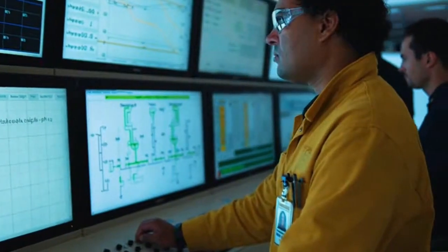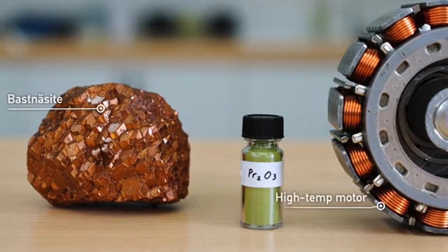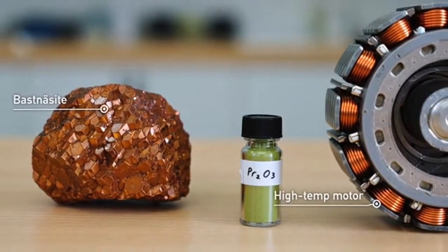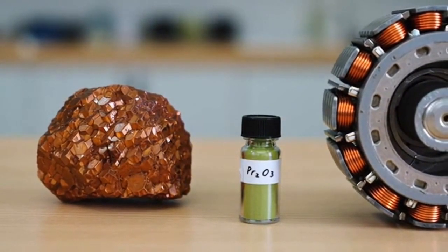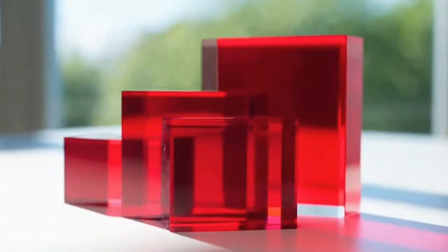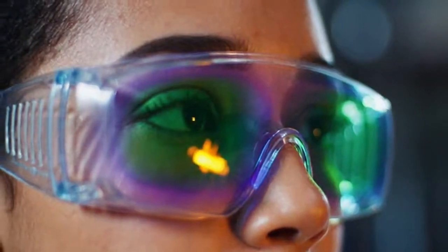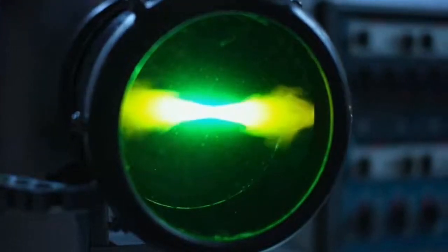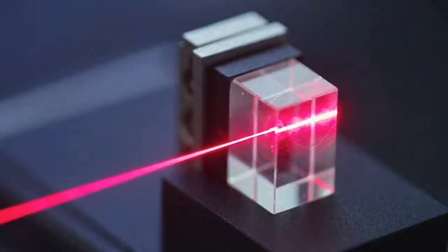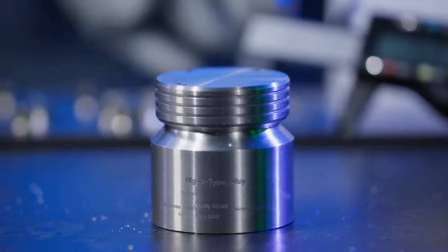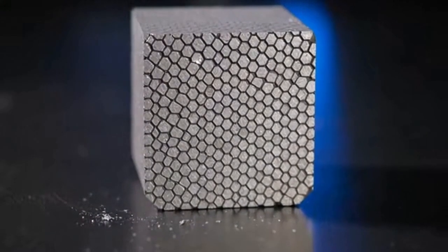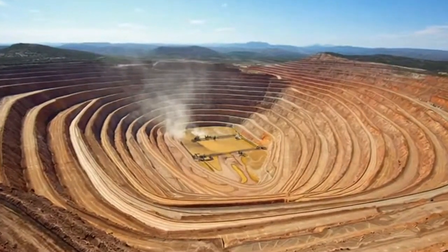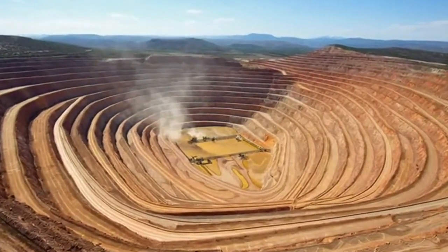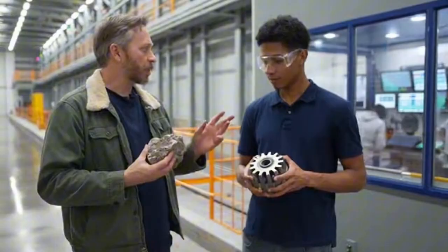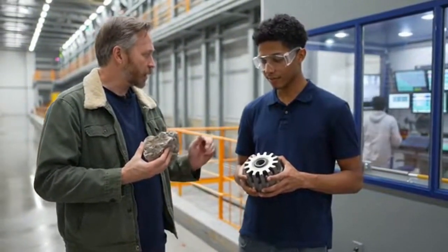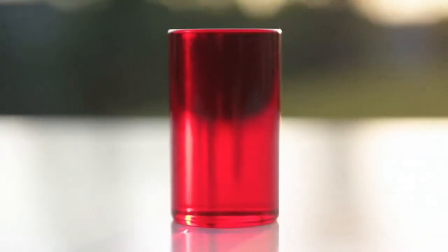There is another route that magnet makers often prefer for flexibility: metallothermic reduction. Oxide, meet calcium under vacuum. Calcium, bless its heart, will take oxygen from almost anything if you heat and pressure it just right. What you fish out, after the reaction has run to completion, is a metal sponge and a calcium oxide slag. Break it apart, pick out the metal, clean it with a salt flux if you must, and now you can charge a furnace with praseodymium, neodymium, iron, and boron to make the alloy you actually care about.